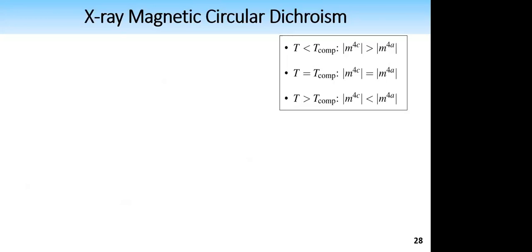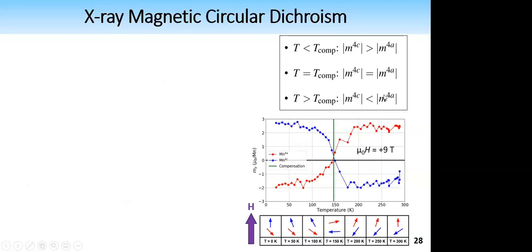First, I wanted to remind you that below compensation temperature, the manganese 4C sublattice is the dominant one, whereas above compensation temperature, the manganese 4A sublattice is the dominant one. So we have performed measurements as a function of temperature in a 9 Tesla applied field. At low temperatures, the 4C moment is positive, whereas at high temperatures, it was the 4A moment.